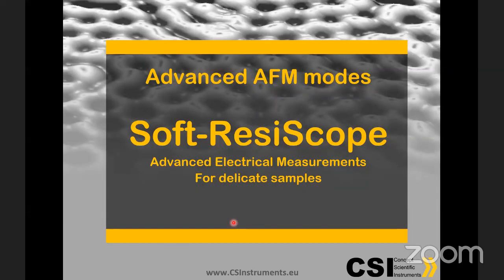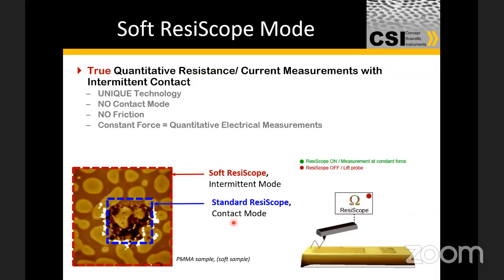And this is really a technique that follows on from the Resiscope, and I'm not going to spend a lot of time on it. We call this a soft Resiscope, and this really was developed because of the increasing needs of organic electronics, because with organic electronics, often we're not able to make a classical Resiscope measurement in the sense that we stay in contact with the surface all the time. But what we developed is an intermittent Resiscope technique, comparable to the classical contact mode